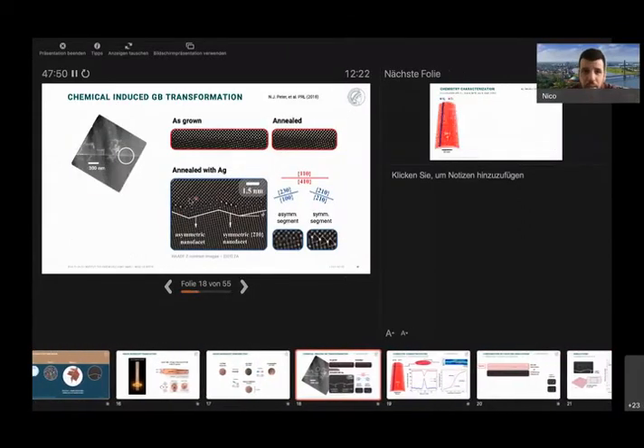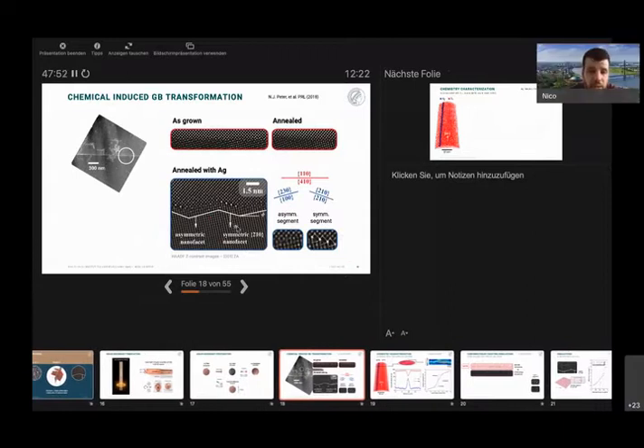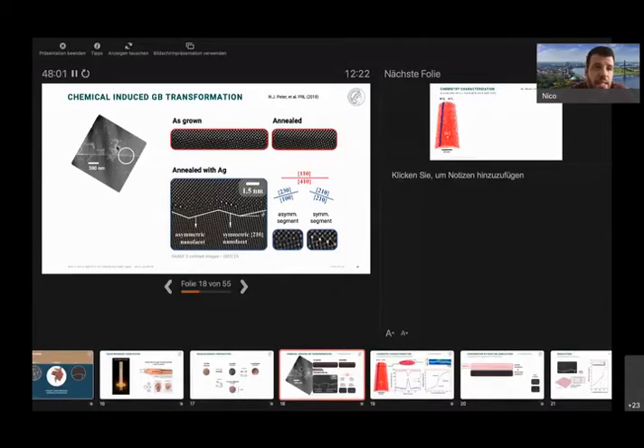Yeah, on the leftmost figure, I see some lines apart from the boundary. Yes, so I have to say this is a STEM image again, HAADF image, and these lines are dislocations. Oh, this is actually, sorry, that's not a HAADF, this is a low angle annular dark field. So it highlights strain contrast. I see. And so dislocations and the grain boundary appear bright. That's usually nicer to show because you actually see the boundary. Otherwise, you don't really see it too much.